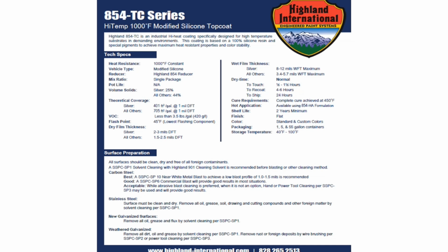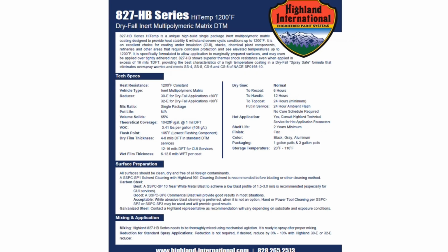Here's just some of the products we talked about very quickly. Our 854 TC, which means top coat series, 1000 degrees, holds color and heat stability. That would go on over top of a primer similar to 827 and go 2 to 3 mils thick. The 827 HB, this is the workhorse that we have that, like I said, goes from cryogenic service from -300 up to 1200. It's a dry fall, has hot application properties, and can be sprayed 12 to 16 mils for CUI service or 6 to 12 mils wet per coat. And you can do a one coat system, or use it as a primer as well.